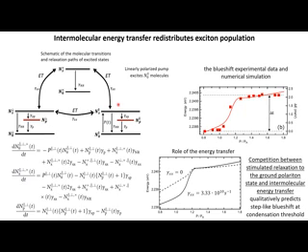But what's going on above threshold? Above threshold, we trigger bosonic stimulation into the polariton state, or polariton ground state. Therefore, this sort of molecules depopulates very strongly into the polariton state, and the energy transfer is not efficient enough to decrease the population of these molecules. And that's why above threshold we have a jump-like blueshift, because we strongly saturate this sort of molecules. But below threshold, the saturation is diluted due to the energy transfer between other sorts of molecules.